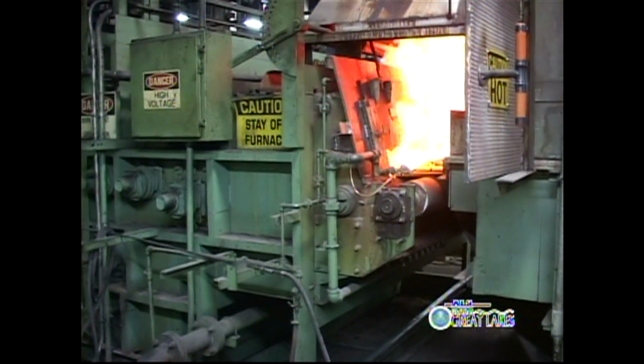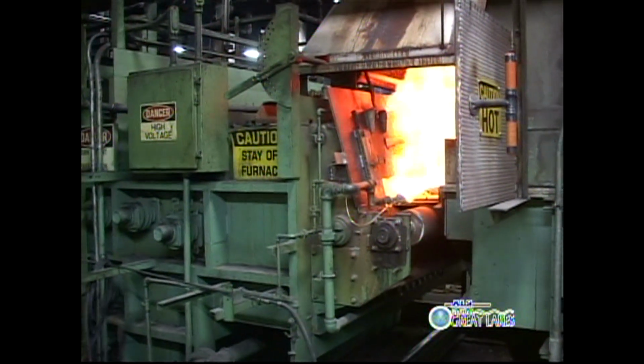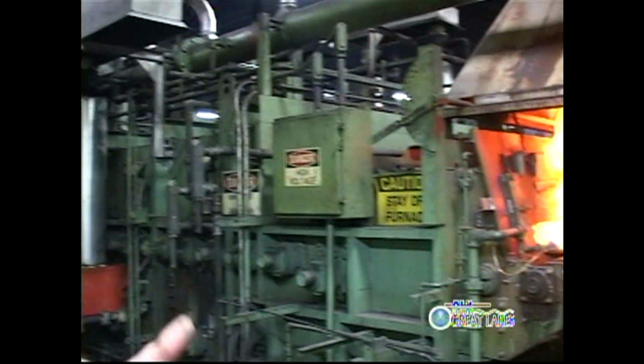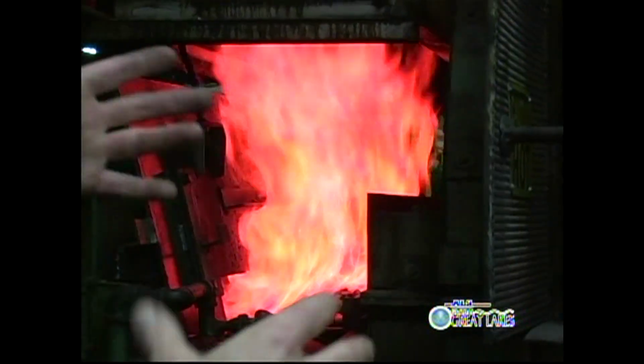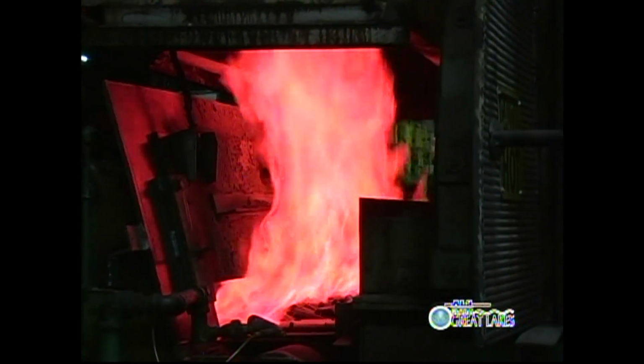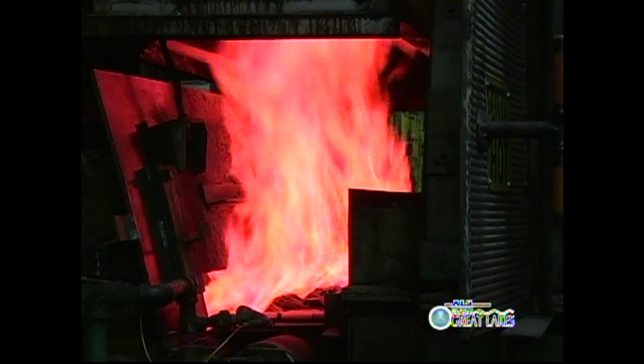These parts are carburizing, so we're adding carbon to the steel. So we have to have it usually set at 1%, a higher carbon potential than what the steel has. This is the 5K belt furnace from the very end of the furnace. You're looking at parts that are processing through the furnace at 1,650 degrees.